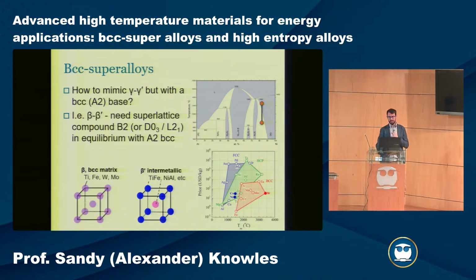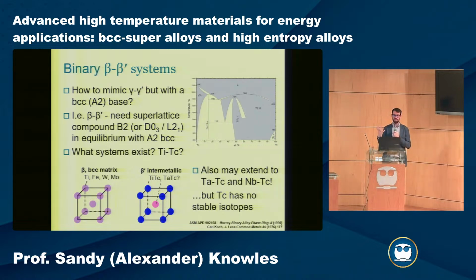So what we need to do is find out which phase diagram is analogous to nickel aluminium. The challenge is not just having the two compounds, the matrix and the precipitate, but you need to have the two being in equilibrium with one another. So this was the search to say, we want the two phases, BCC and ordered BCC, in a two-phase equilibrium. Which systems exist? We can search phase diagrams, and we can also use computational methods. And of the binary systems, there are really very, very few.